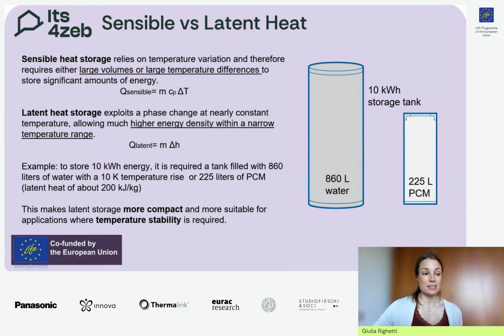This example, I think, is very illustrative, because to store 10 kilowatt hours of energy, we require roughly 860 liters of water with a temperature rise of 10 kelvins. The same amount of energy can be stored in around a quarter of the volume, about 225 liters of PCM with a latent heat of about 200 kilojoules per kilogram. So this is why latent storage is more compact and attractive for applications where temperature stability is required.